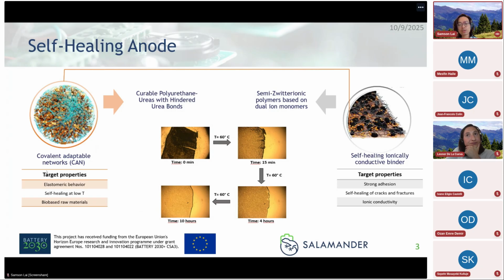And it can also be derived from bio-based materials, so we have that circularity built in. Our family is called curable polyurethane ureas with hindered urea bonds. I'll get into that a little bit later. The other type of polymer that we have is the semi-zwitterionic polymers. These are very similar. They have self-healing properties, but these are less temperature activated, and more present throughout the entire anode.